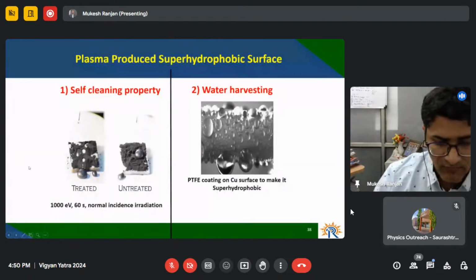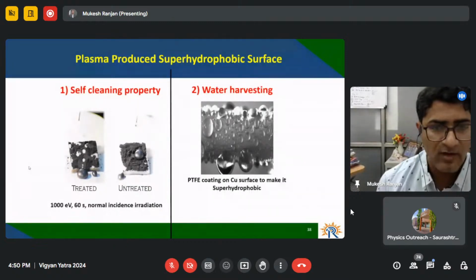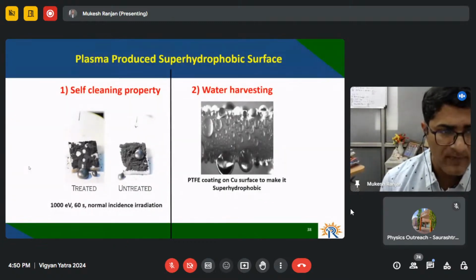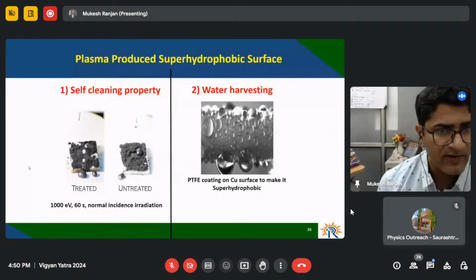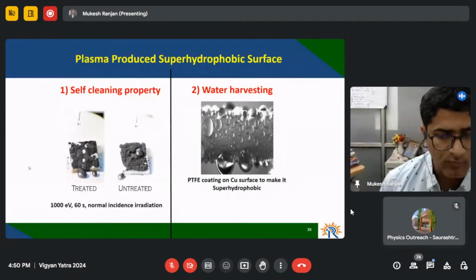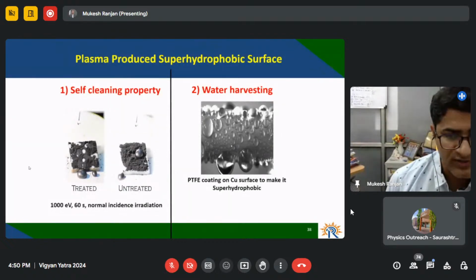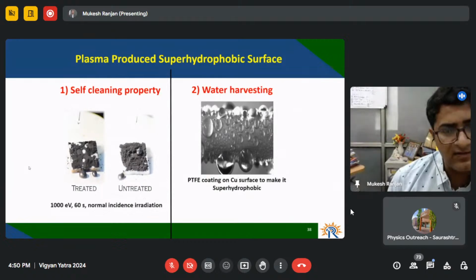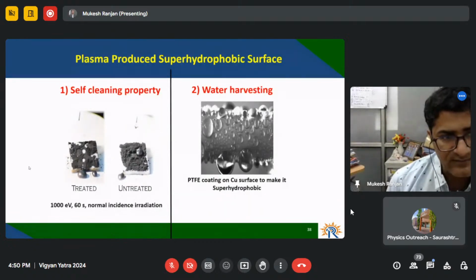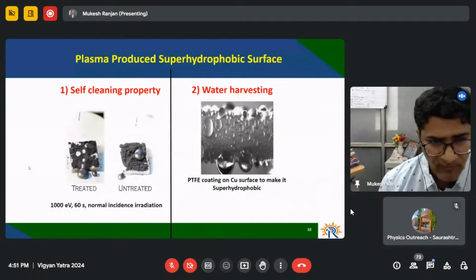So now you have seen that nowadays people are installing solar panels on their rooftops, and there's a lot of problem of dust accumulation. So when you have dust accumulation on the surface, you need to wash it. Okay, so you might have seen that people are using a shower to wash their solar panels. But the fine dust is very sticky. Okay, so if you have a top layer which is transparent, and it has nanostructures giving super hydrophobicity on the surface.